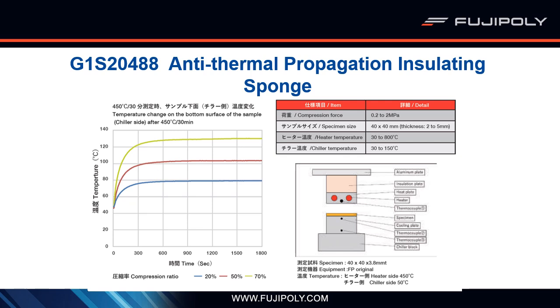You can see the bottom line on the graph here, which is our 20% compression measurements. Again, we're running the hot side about 450 C, and you can see we're keeping the cold side a little under 80 C. So pretty good temperature gradient there. We're talking about close to a 370 degree difference between the hot side and the cold side. And as you can see, as we increase the compression, of course, that's going to change, right? We're reducing that distance between the heat source and the cold side. We're also evacuating a lot of that air as we start to really compress that sponge. So you start to get basically what amounts to a reduction in that thermal resistance.